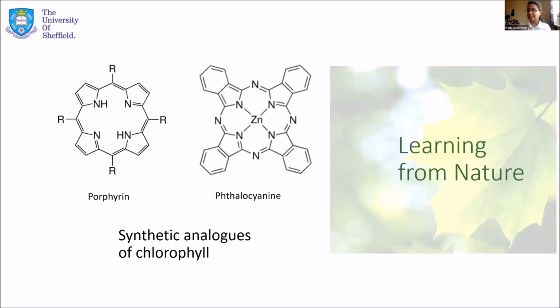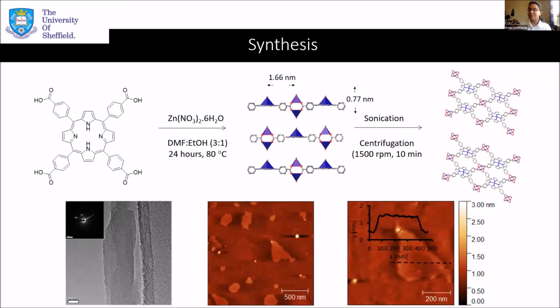So looking at my project, we started off by testing porphyrin-based structures, which are synthetic analogs of chlorophyll and make sense when one of the applications is light absorption. So this is how the material is made. Since these materials have a modular structure, you can tune the functionality by choosing the organic linker of choice for the particular application. So here we have the porphyrin system that is linked with the metal cluster to form the 3D MOF structure, which is then exfoliated to form the nanosheets that are known as MONs.